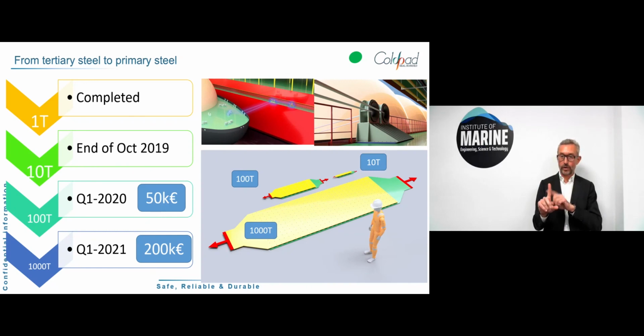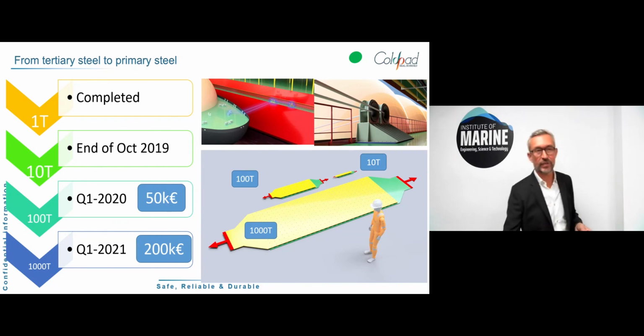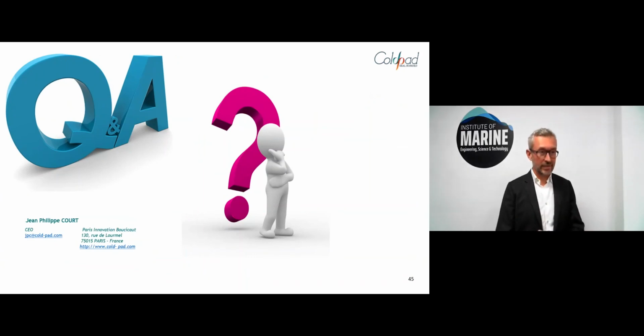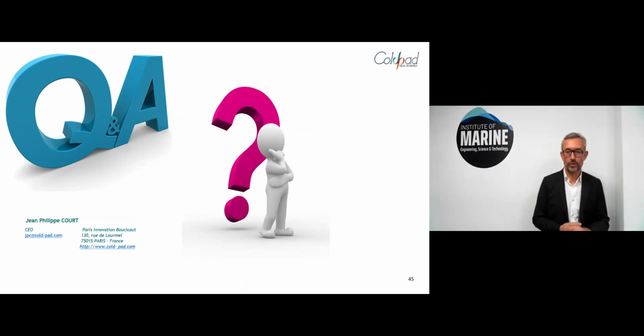But the fact that we had a failure on 1 of 4 didn't generate a catastrophic failure. It was a crack stopper, because all the load was taken by the 3 others. And we could go up to 25 tons, and at 25 tons we needed to stop the test because we reached the maximum capacity of the testing machine. So we are very confident for the 100 and 1000. I think that's it. I will be delighted to answer your questions.